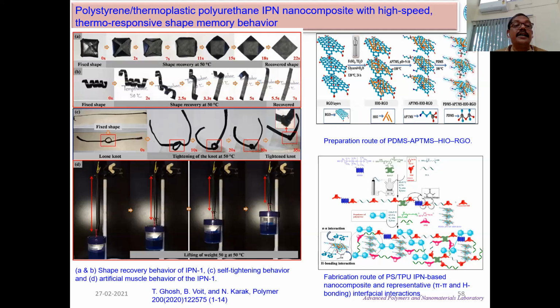Recently, we have produced an ultra fast shape memory material, a thermoresponsive shape memory nanocomposite, by using functionalized polydimethyl siloxane and silane coupling agent with hydroxy iron oxide and RGO based polyurethane nanocomposite, where we have seen that even within 22 seconds you can recover the original shape after exposure to heat of about just 50 degrees centigrade.